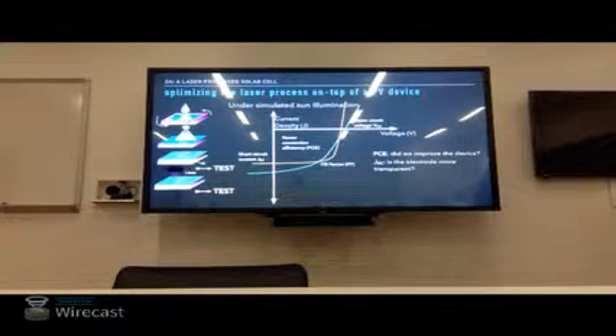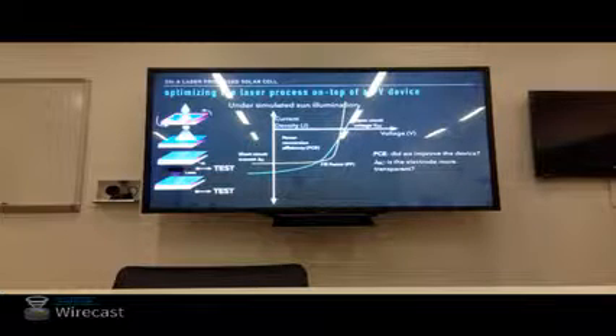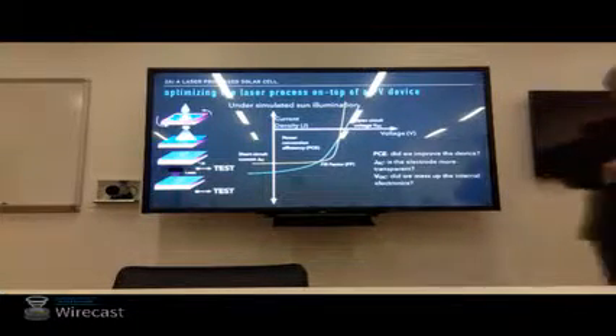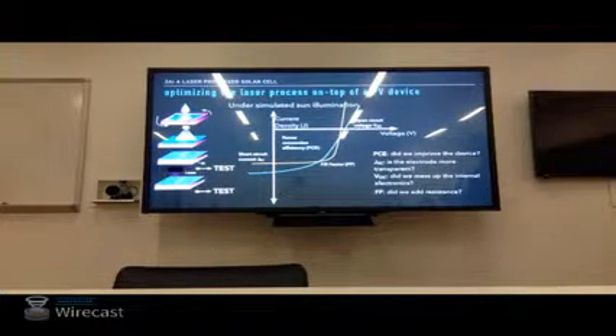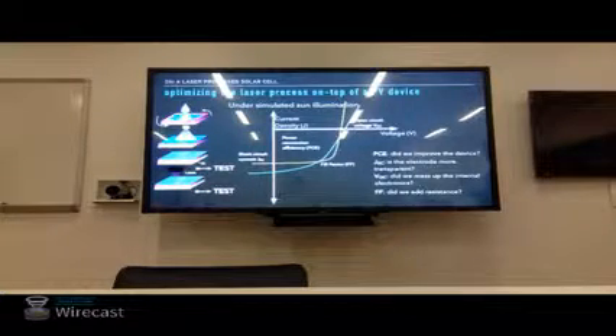The power conversion efficiency is going to tell us, did we improve the device? The short circuit current, for the most part, is going to tell us, is the electrode more transparent? Are we getting more light? Light causing current. The open circuit voltage will tell us something about whether we messed up these internal electronics. And the fill factor is going to tell us something about whether we added resistance. And again, this is what we're afraid of, is adding resistance.